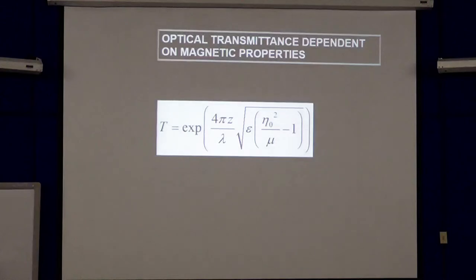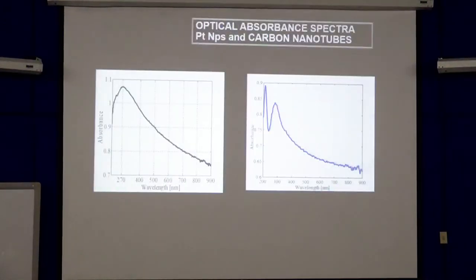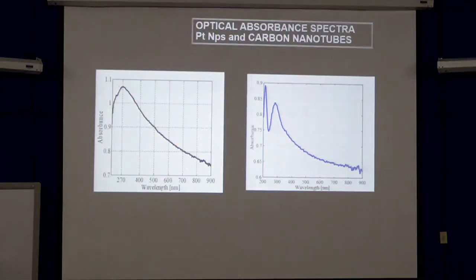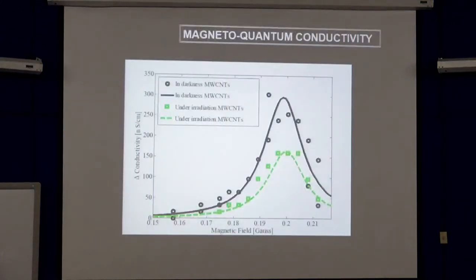Okay, this is the equation for the transmittance that is related to the permittivity, permeability and the impedance. And this is the spectra of the sample. These are carbon nanotubes, and carbon nanotubes with platinum decoration. The conductivity in the sample produces a magnetoquantum conductivity. This is an effect related to an increase in the magnetic field to get a peak, and then a decrease of the conductivity with the change of the magnetic field.